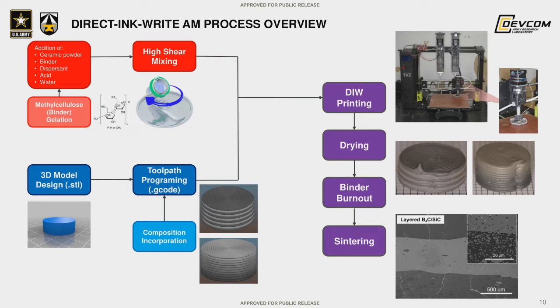So once we have the inks ready and the designs, we put them together and actually print out our parts, which then follow a drying process to remove excess water from it, then a binder burnout step where we remove the polymer binder, leaving us with only ceramic powder, and then finally the high temperature sintering step where we convert basically a porous sort of sandy powder part into a fully dense ceramic component.